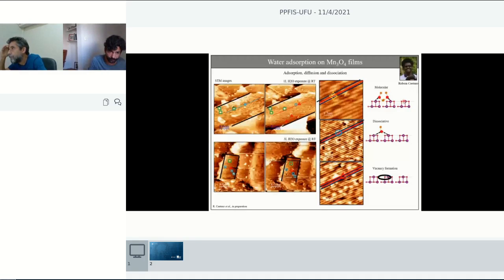Here are some examples where you see bright protrusions, that's the way we can say, or dark areas. Everything that's bright is higher. Everything that's dark is down. It's like a morphology image, but it has this interpretation about the electronic structure. And then here in this image, we are following different water exposures, in the work of Huben. In the STM image, we can assign and find from these indicators here where these water molecules are sitting. So then we can try to find a model of which position of this line the water molecule sits.